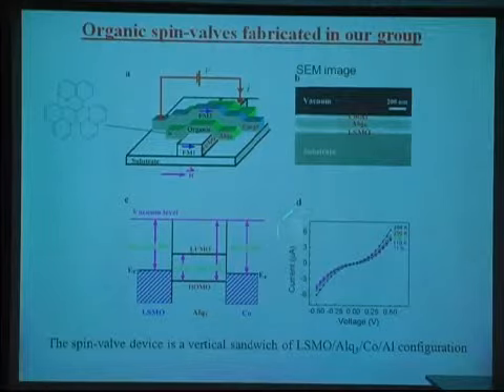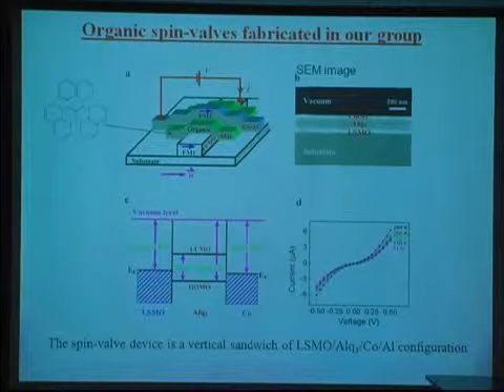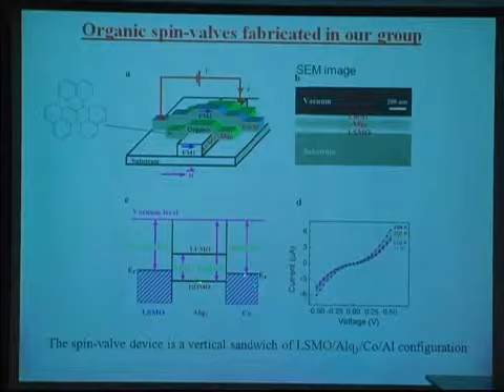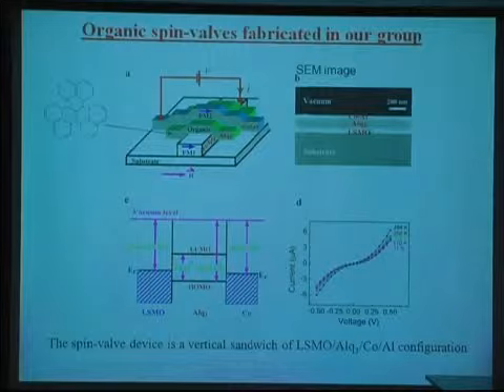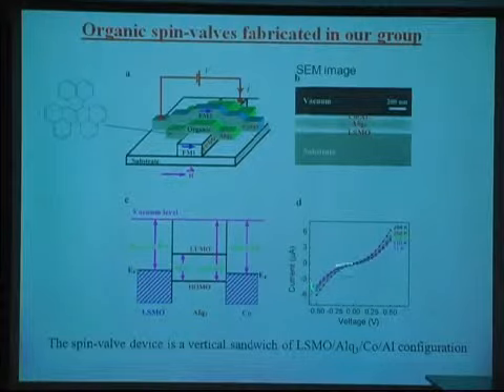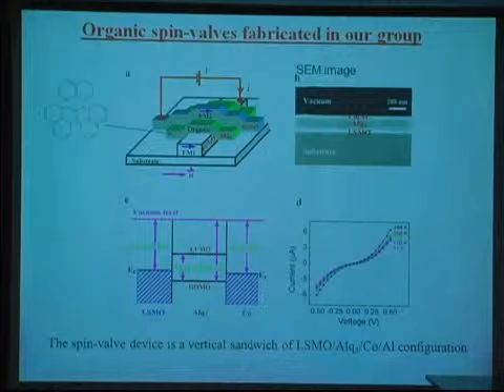And here is the band diagram of the device. You can see the Fermi energy of LSMO and the Fermi energy of the cobalt are close to the HOMO level. So these are very good materials for hole injector and detector. The IV characteristics show you that this is really a unipolar device.